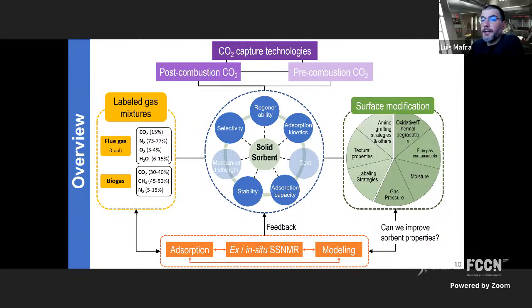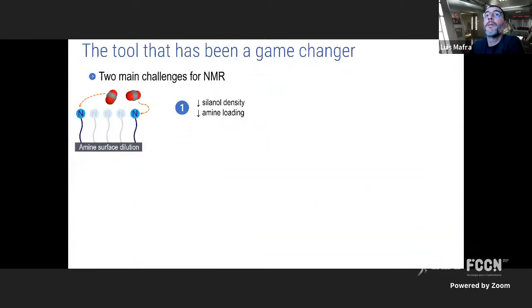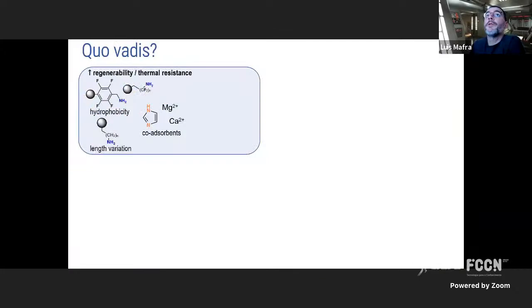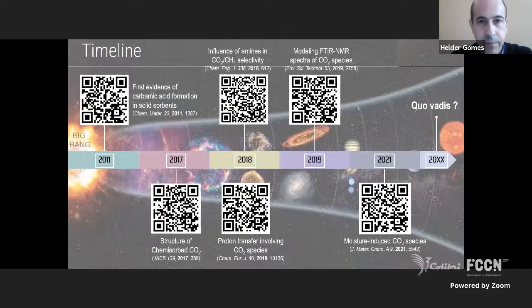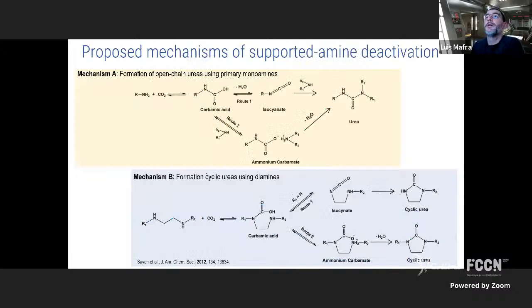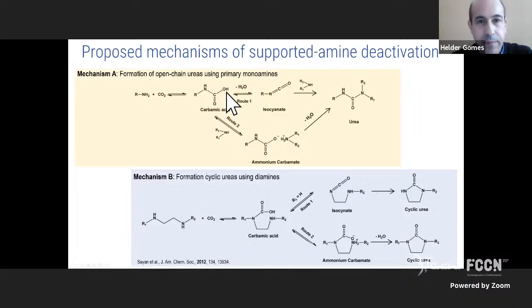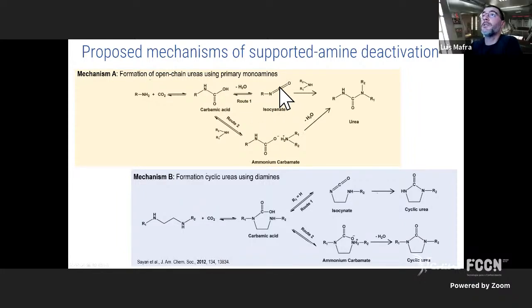Yeah, this is a very complex problem. I avoided going into that because of time constraints, but basically I can show you one slide. When you absorb, you have certain mechanisms like this one that are inspired by solution amines, and people transport all these solutions to the solids, okay, without much proof. And what happens is once you absorb CO2, this amine, for example, you have many routes. You can go to isocyanate intermediates with dehydration, or you can have a second amine interacting, and with further dehydration, you can form urea. Once you form urea, these molecules are very stable, and you deactivate the material basically.